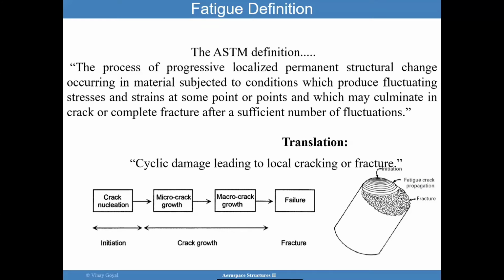fatigue is basically cyclic damage leading to local cracking or fracture. And the process for fatigue failure is crack initiation, crack nucleation, and we call this the initiation aspect. And then that crack will go under micro crack growth. And from micro, it turns into macro, and then it turns into failure. On the right-hand side, and I'll be covering this picture quite a bit, the initiation will occur at a particular point on the surface and then emanate from that point outwards. And I'll go into more details about some of the phases of fracture.